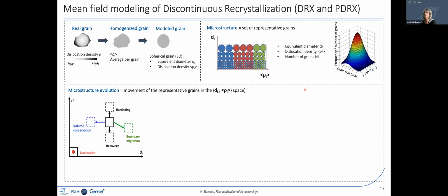If a grain grows, its dislocation density will also decrease because there are no dislocations in the volume swept by the boundary movement. And because of volume conservation, you also must have grains which decrease in size, since some of them grow, others have to shrink. That's it.